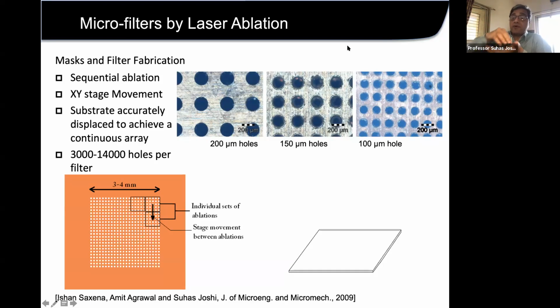So now I can have a mask with 100 holes, and the mask can be larger, but those 100 holes image can now be reduced. And then I can put it on a surface like this is one image. At that point, I do some pulsing, then go to the next step somewhere here, or here, and like this, it is a 3 to 4 millimeter place. It's a very small space, because I can now reduce the image. I can make it a very small image.